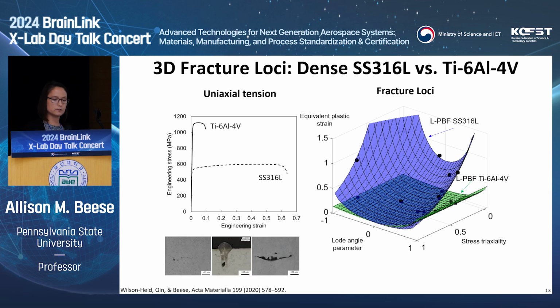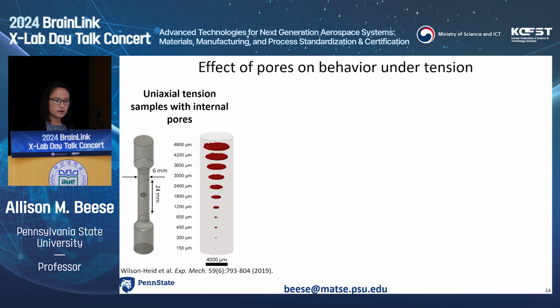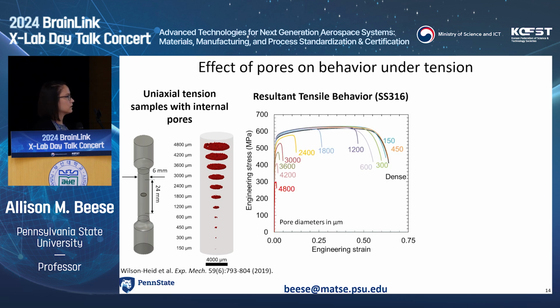So the other thing we wanted to look at is, well, what if we have defects? A big concern would be, if I find a defect in one of my additively manufactured parts, do I need to throw it out, or can I still use it? What are the implications of this? To study that, we've fabricated samples that have intentional defects within them. We fabricate tensile samples, for example, with a single pore at the center, with a wide range of sizes, where we're interested in the relative size of that pore. And then we can see how our stress strain curves are impacted by those defects.